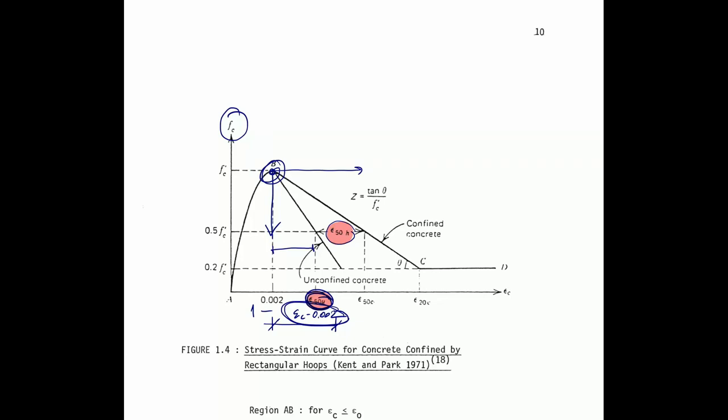So the microstructure between the paste and the aggregate, okay, that interface generally starts cracking. Under tension, the bonding is lost, and once you reach the peak, after that the crack propagates. So bonding is decreasing, and then it comes down. So you have the decreasing stress. But up to one point, even though you have the disintegration of the bonding, if your concrete is well confined, it does not fall out, and it can maintain.